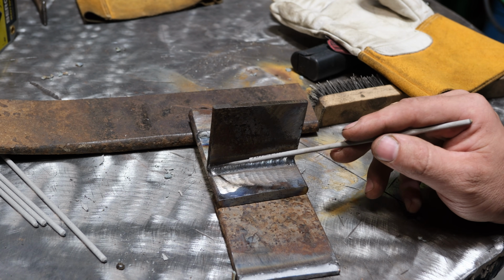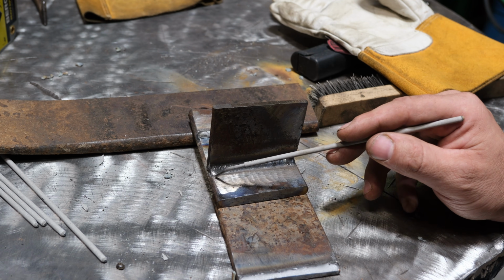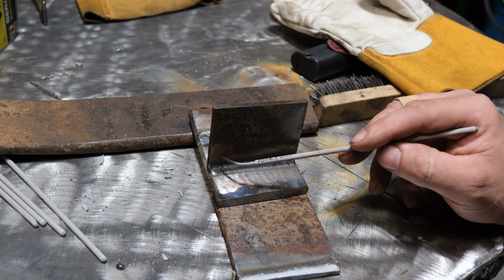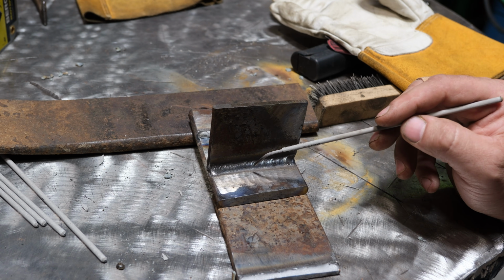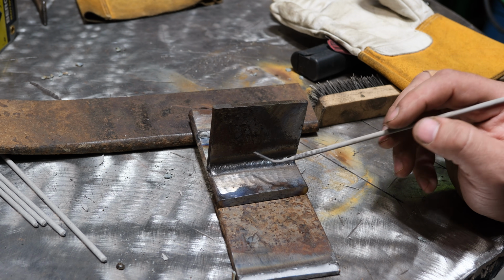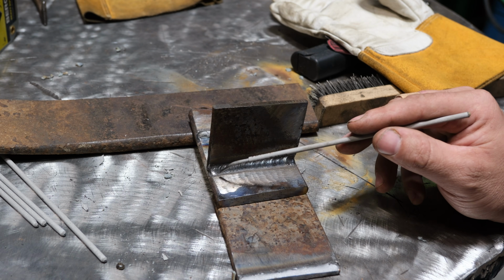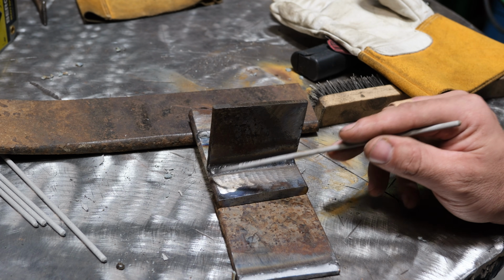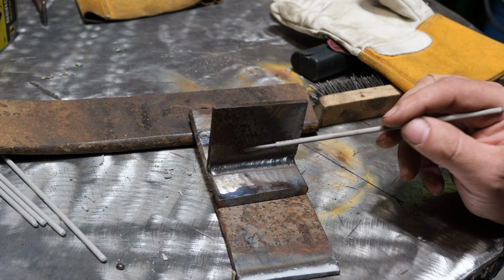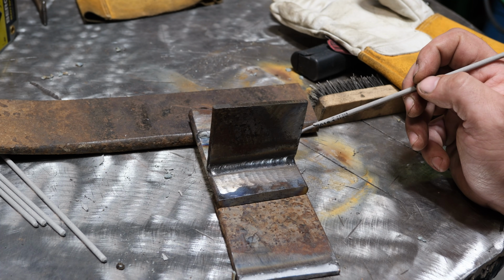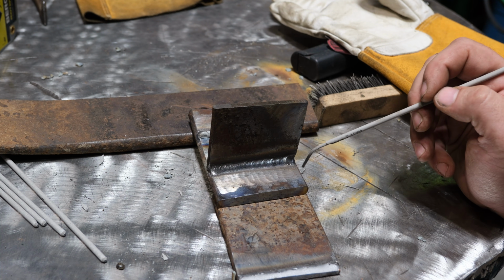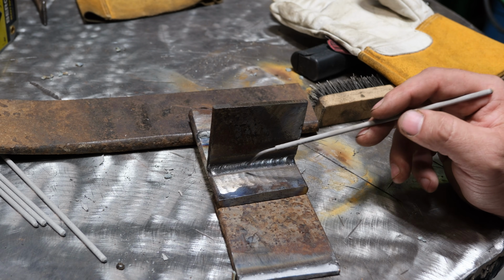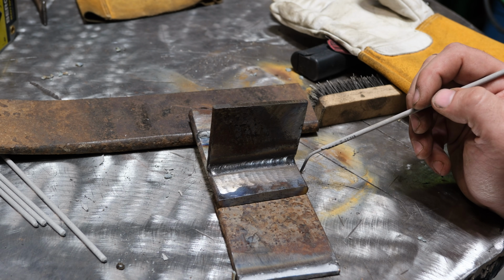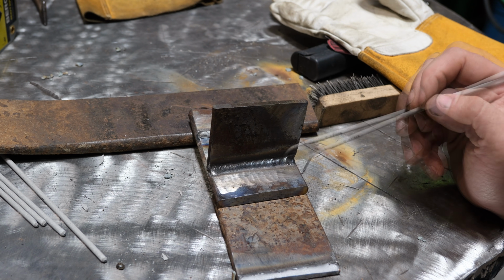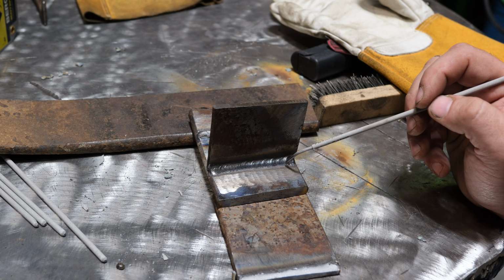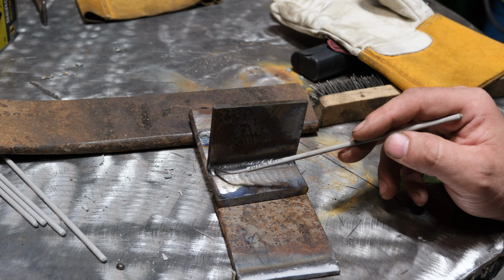Do not do this fast. If you just sit and pump a lot of heat in one area, by time you get other areas up to temp, you're probably going to overheat the area you initially started with. So you want to take it slow. You want the whole material here and here, preferably dull red all the way through it. You don't want to see, especially if it's a thicker spring piece, where it's just red on the surface and there's nothing even remotely as hot on the back side. So the whole area needs to be dull red.